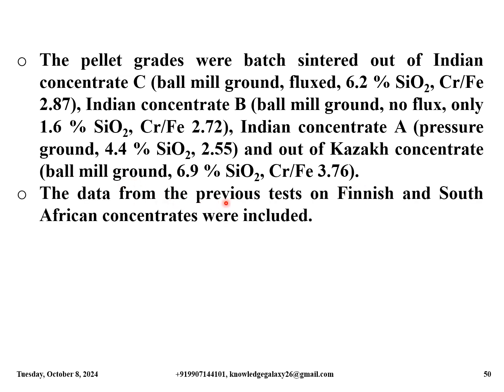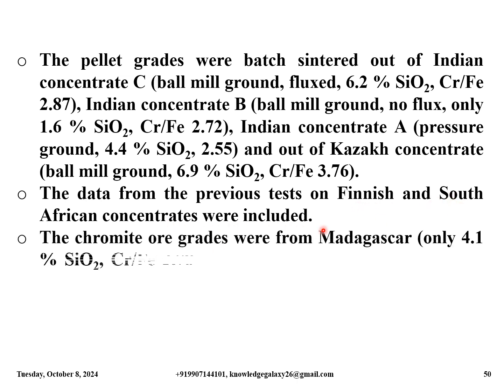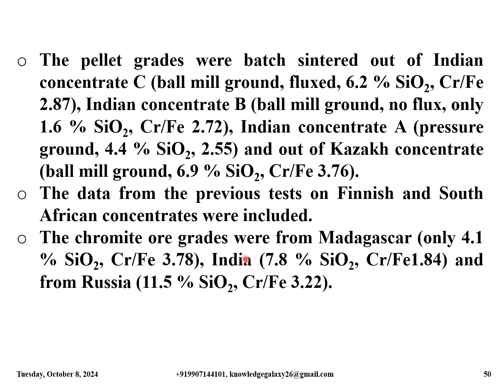The data from the previous tests on Finnish and South African concentrates were included. The chromite ore grades were from Madagascar, only 4.1% SiO2 and having Cr/Fe ratio of 3.78; India, 7.8% SiO2 and Cr/Fe ratio of 1.84; and from Russia, 11.5% SiO2 and Cr/Fe ratio of 3.22.